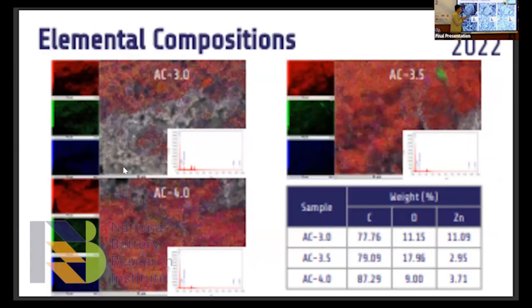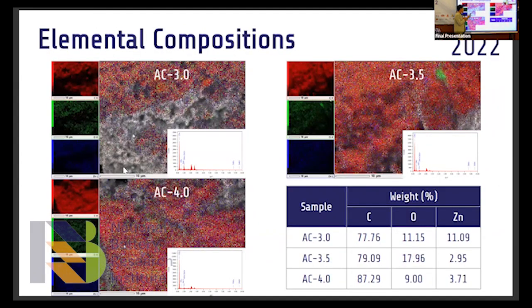Next. The next one is the result from EDX. The elemental composition of carbon, oxygen, and zinc is listed in the table. As seen in the figure, the carbon, represented by red dots, increases sequentially with the activation time. Thus, it affects the carbon percentage, which is inversely proportional to the impurities, and vice versa. Whereas the zinc, as a result of activation, does not degrade sequentially, which signifies that the activation time doesn't reduce the zinc quantity.